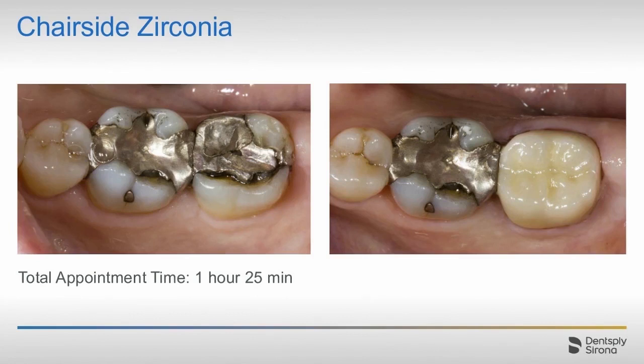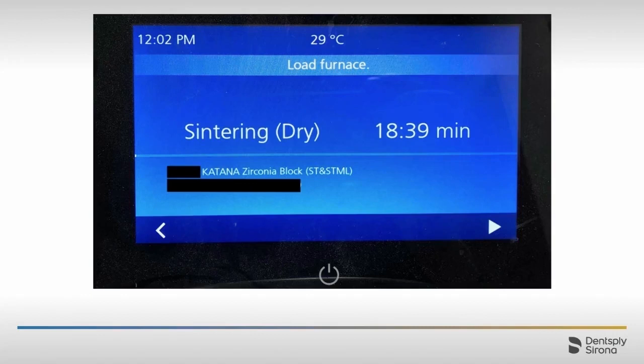When zirconia was first released, I said we better be efficient enough to do it in 1.5 hours. Otherwise, it doesn't make sense for us as chairside dentists. And you can see with these different workflows, the dry milling, the fast milling, the fast sintering, we can actually do these restorations quite efficiently in our office.